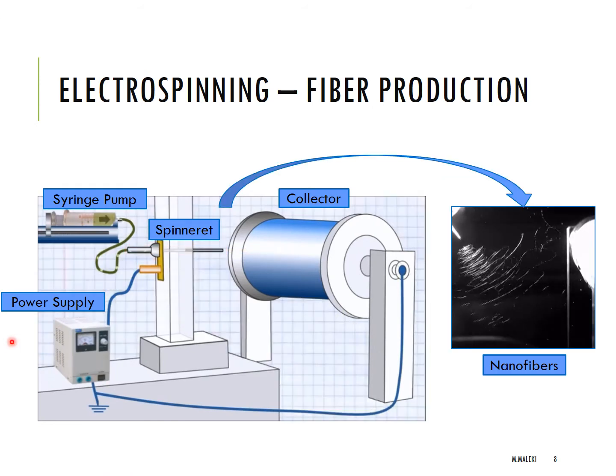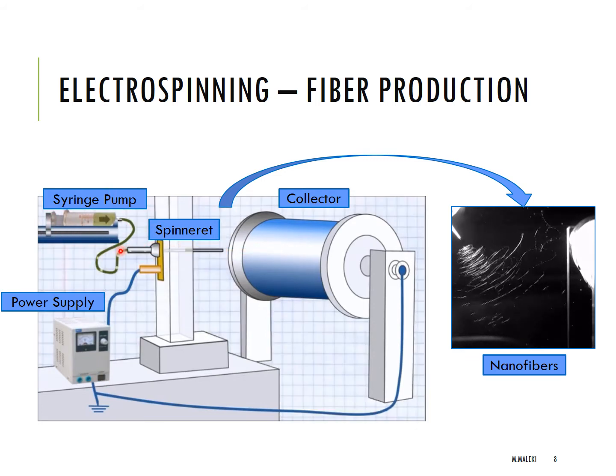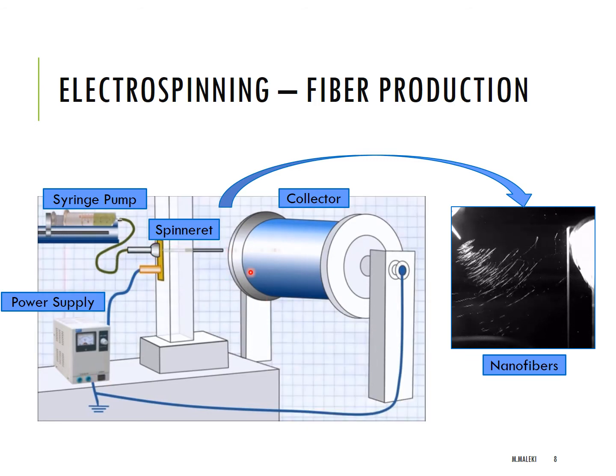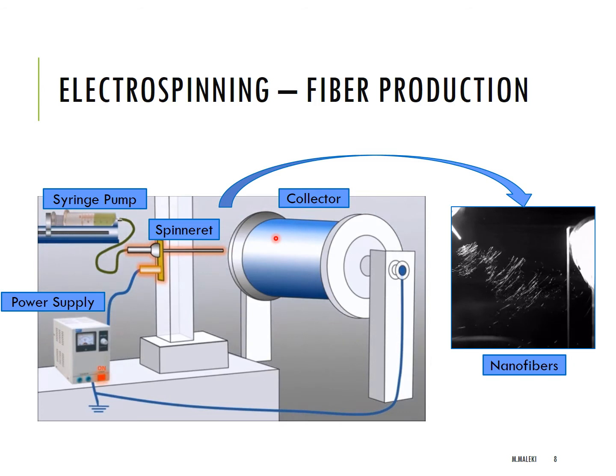This slide shows how electrospinning works. First, the polymer solution is placed into a syringe and then pushed to the tip of a spinneret by external pumping to generate a flow. When a droplet is formed, an electrical voltage is applied between the tip of the spinneret and a collector placed in front of it. The solvent quickly evaporates from the jet and solid nanofibers are finally deposited on the collector.